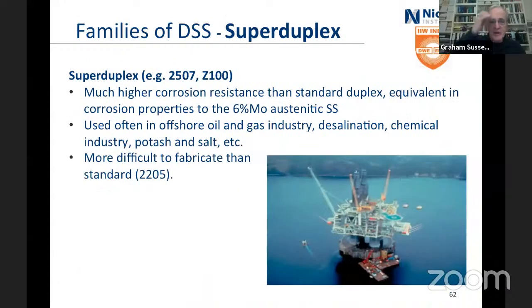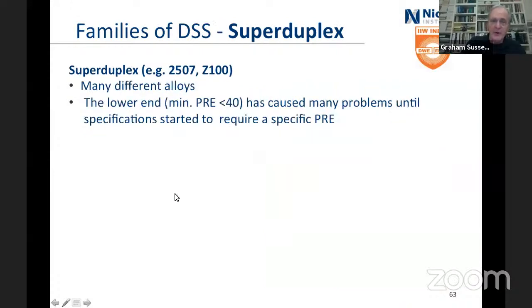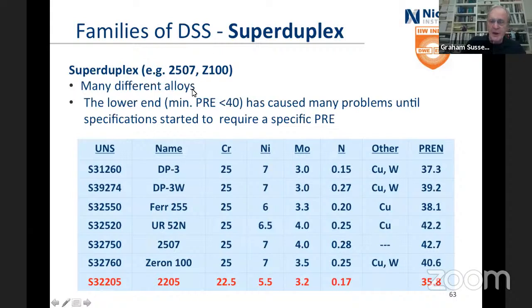Super duplex, the Sandvik one and the Rolled Alloys one. More corrosion resistant, 6% moly, so that gives its own problems in welding, and offshore, and it's more difficult to fabricate. The other super duplexes, really, there's a hell of a lot of them. There you are. And okay, let's look what's happening here. Bit of copper because you are interested in perhaps resistance against acid. Tungsten just for the corrosion resistance. And then moly, reasonable amount of it. Nickel to keep it as a duplex.